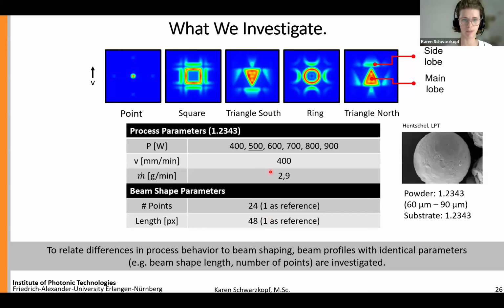Short overview again of the process parameters. The experiments that I'm going to talk about in the next slides were all conducted with 500 watt, a feed rate of 400 millimeter per minute, and a powder mass flow of 2.9 gram per minute. As material, a hot working tool steel was employed, which is also known as H11, and the substrate was made of the same material.